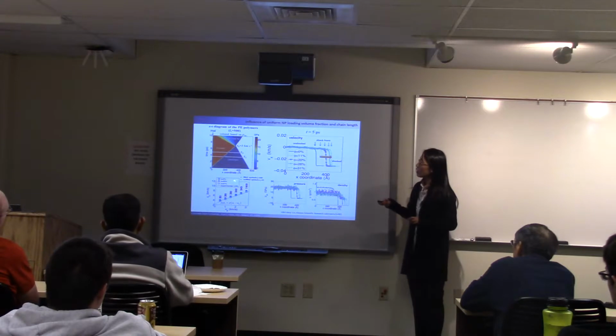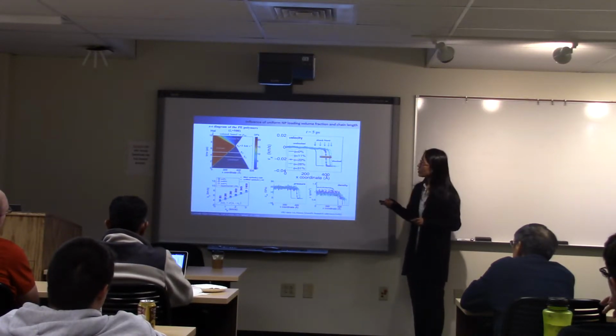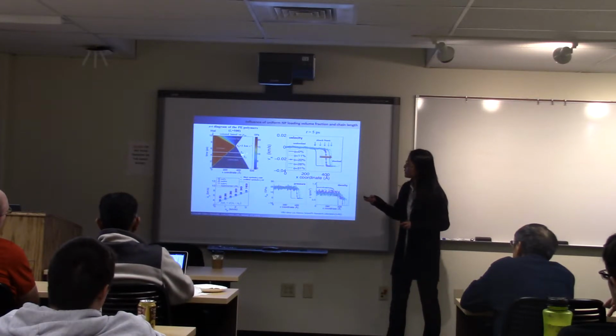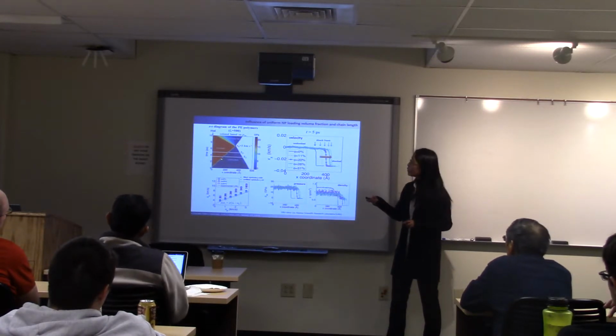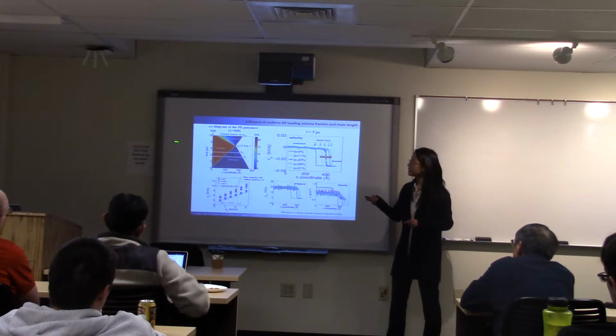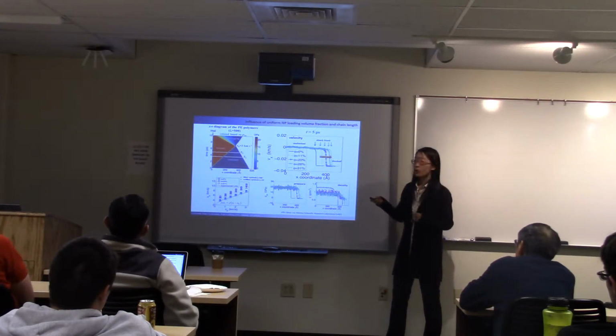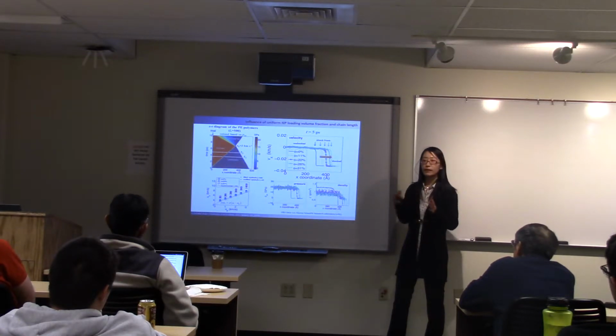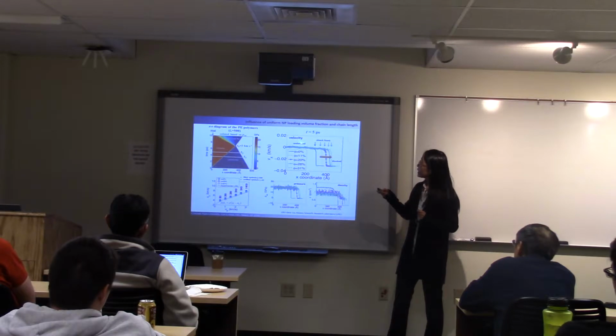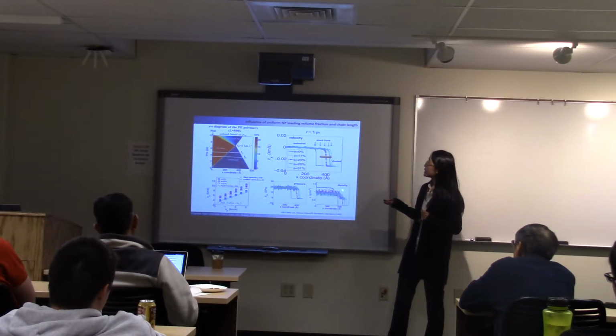And here is a position-time diagram of the polymers under shock. We see that at T1 and T2, with time, this shocked region is linearly increasing while the unshocked region is decreasing, which shows the steady propagation of the shock wave. Along the time, we also record the velocity, pressure, and density.